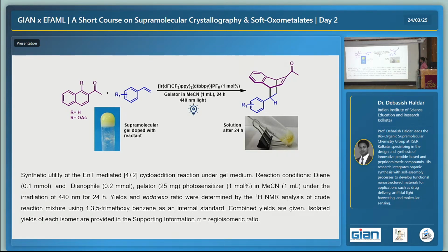After 24 hours under 440 nanometer light, the gel actually melts. And so we realized that something is happening with the gel. So we analyzed and we figured out that yes, the reaction is happening. So now this is an open tube, a test tube.